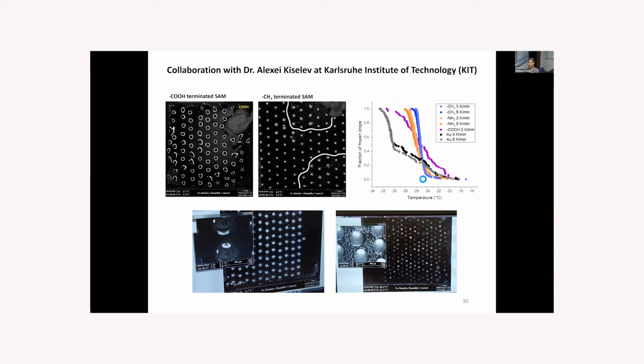So we have tested the methyl groups, amino groups, and carboxylic groups of C16 alkanethiols. And we can see, as expected, that the COOH, the most hydrophilic monolayer, would start to freeze the water molecules before the amino and the methyl group terminated surfaces. And this is a very promising result, but we need to repeat it, and we also add the OH group in order to have a better comparison of many functional groups.